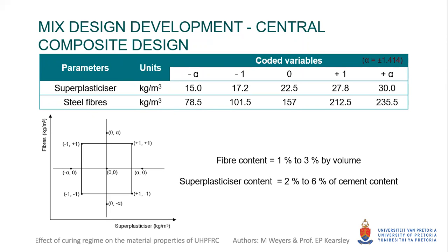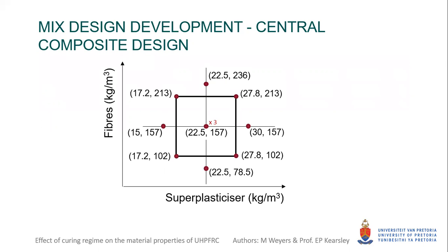The response surface design has an improved quality of prediction when it is rotatable, which is influenced by the alpha and the number of center points. Fiber content was varied between 1% and 3%, while the superplasticizer content varied between 2% and 6% of the cement content. Each one of these points then represents a mix design.